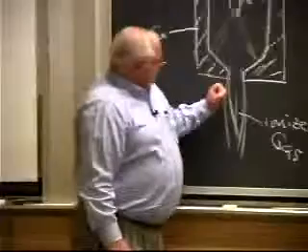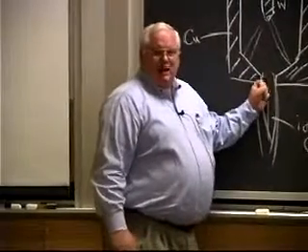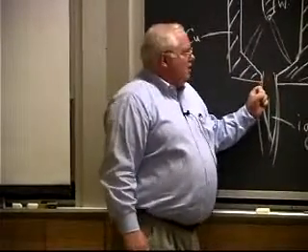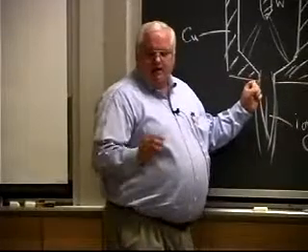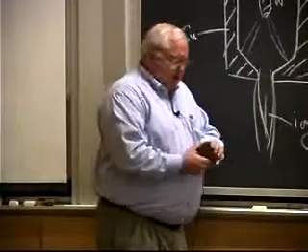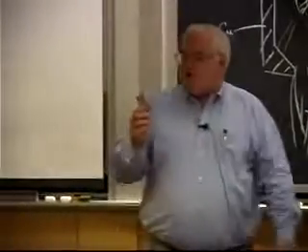In any case, plasma cutting has kind of taken over because it has a productivity advantage, a quality of cut advantage, and it can cut other materials. This is a piece of half-inch stainless steel, which I'll pass around. It's been plasma cut. In this case, there's no chemical reaction generating heat. There is a boundary layer, but you're basically punching through the whole thing, so you're sweeping part of the boundary layer away. And you just melt through the whole thing with just total thermal energy.